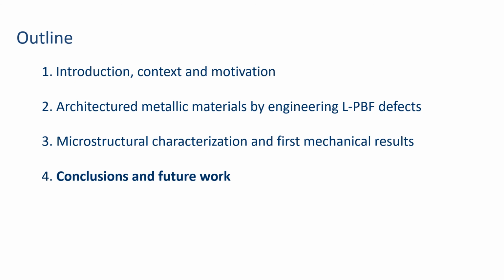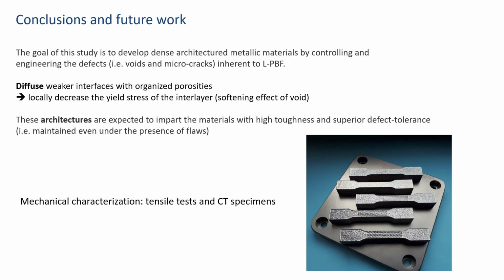And now it's already time to jump to the conclusion and future work. In this study, the goal was to develop dense architectured metallic materials by controlling and engineering the defects. In this case, I focused on the results for the voids and microcracks, which are associated with the LPBF process. And we have been able to generate diffuse interfaces with organized porosity within a matrix, and these interfaces had locally a decrease of the yield stress of the interlayer due to the softening effect of the voids. And we hope that these architectures will impart materials with high toughness and superior defect tolerance.